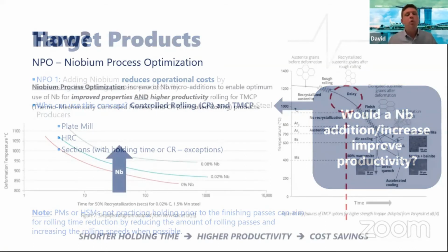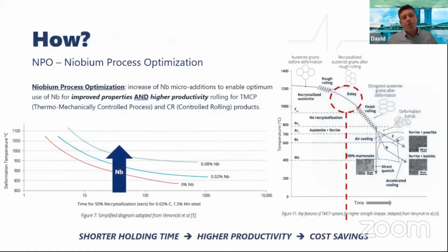What niobium can do is, due to the very strong effect of niobium on the recrystallization process, by slowing down or even interrupting the recrystallization from happening, niobium can help design the rolling process to be faster, reducing the delay time between roughing and finishing, or sometimes reducing the total rolling time, increasing the rolling speeds in a way that you can have a higher productivity to produce the same amount of tons and save costs.